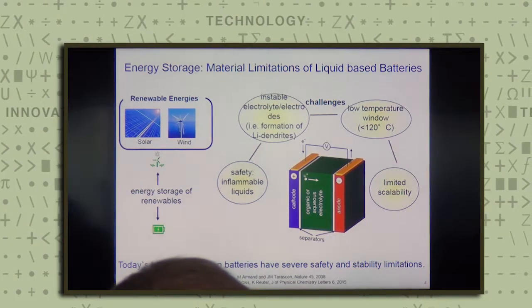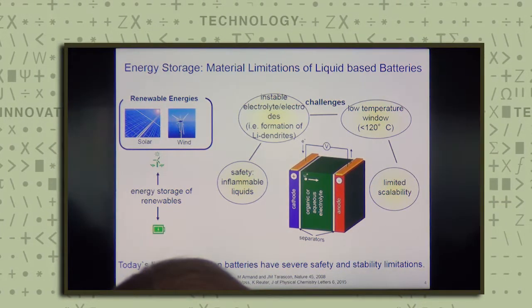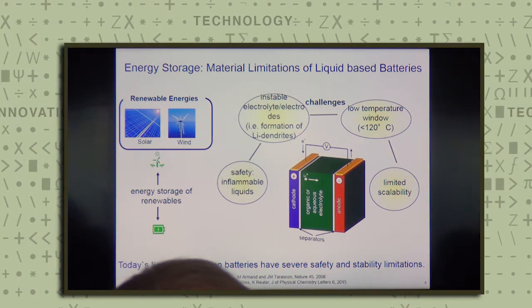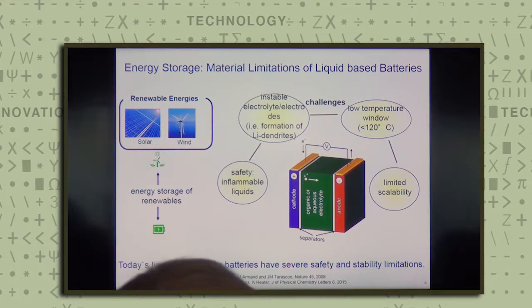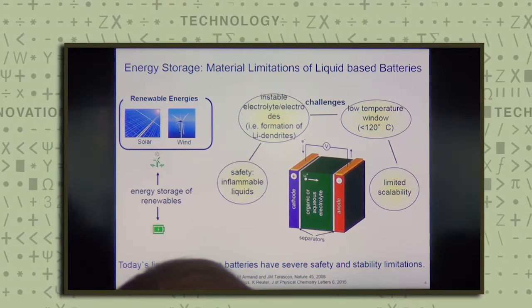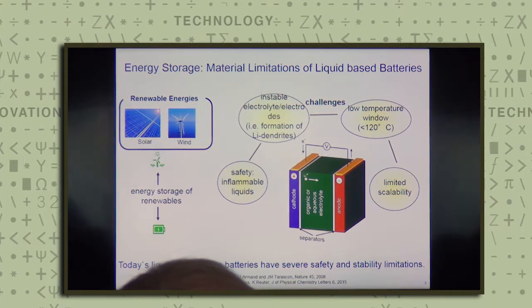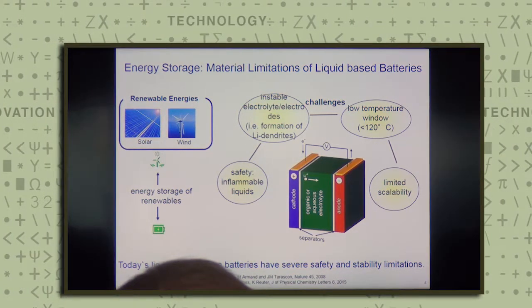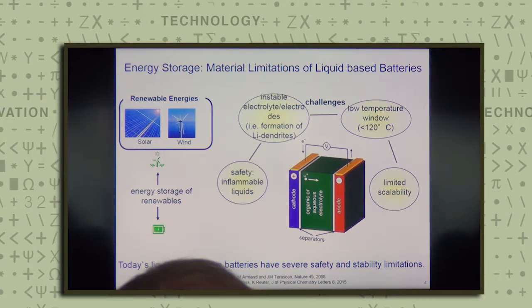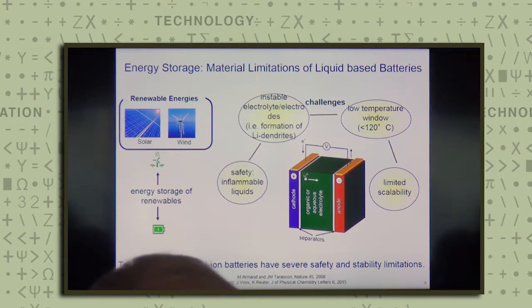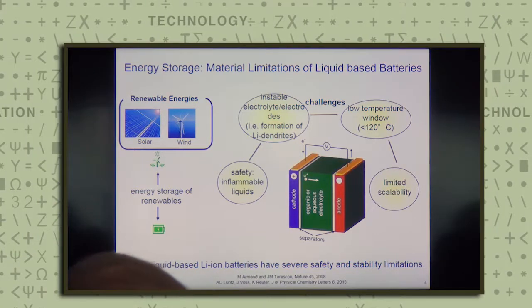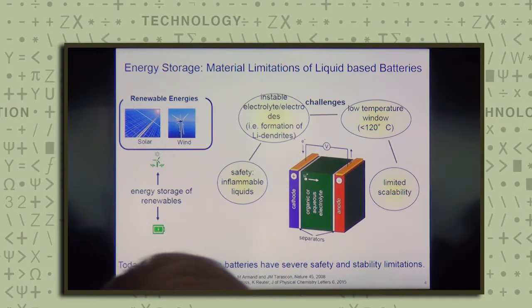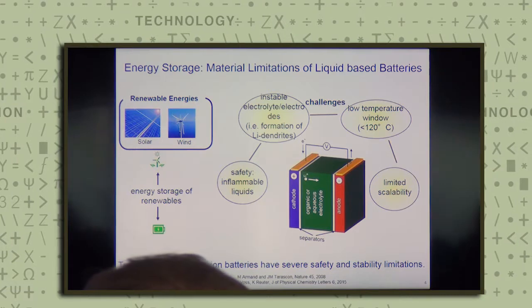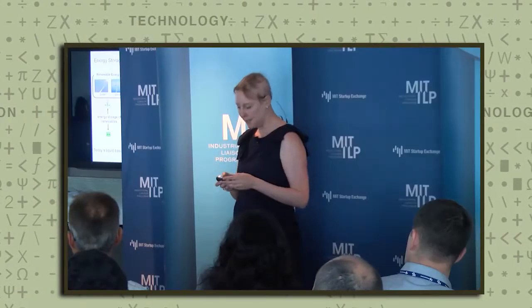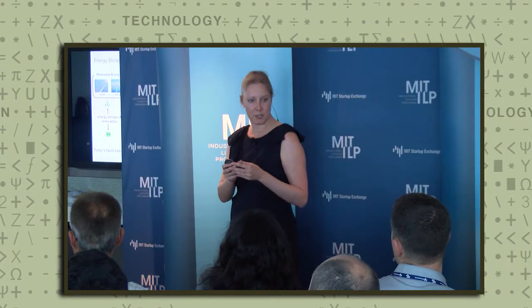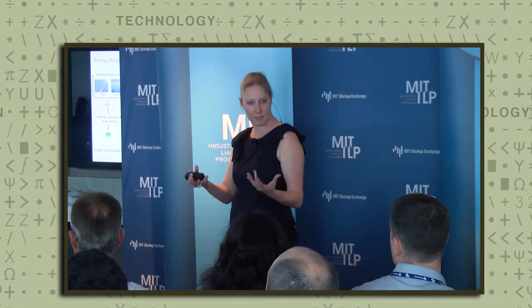The general motivation, as we have heard this morning, is to go into solid-state batteries because you can significantly increase the safety. In a solid-state battery, you would replace a classic liquid-type lithium electrolyte that you would have with a polymer by a solid-state ceramic compound where the lithium is structurally encaptured. And you can use that ability to have open designs even of batteries that won't inflame anymore in air. We all know those pictures that we have seen in the morning, that this is definitely a safety concern. The other aspect of interest is that you can enlarge the thermal operation window to go strongly above 120 degrees C.